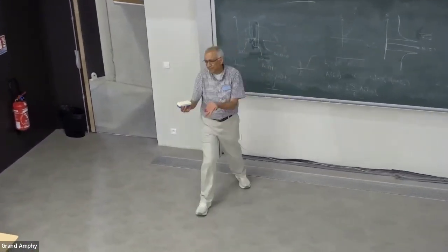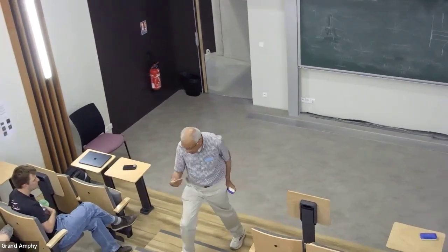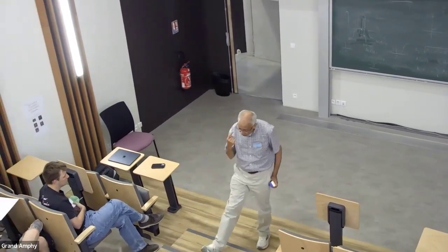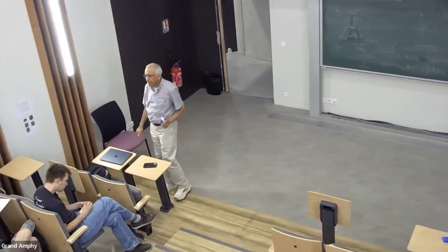That's a very different story. As you know, the band edge singularity in some band has a characteristic form. If you have a parabolic dispersion in one dimension, you actually get a 1 over square root E. If you have a parabolic dispersion in 2 dimensions, you get a jump discontinuity. If you have a parabolic dispersion in 3 dimensions, you get a square root E dependence. But you can just work that out. It's just algebra. Yeah, I guess I confused 2D versus 3D. It's just that the dispersion is showing something, and that's why it's happening. You have a lot of states there. You just have to do the algebra.